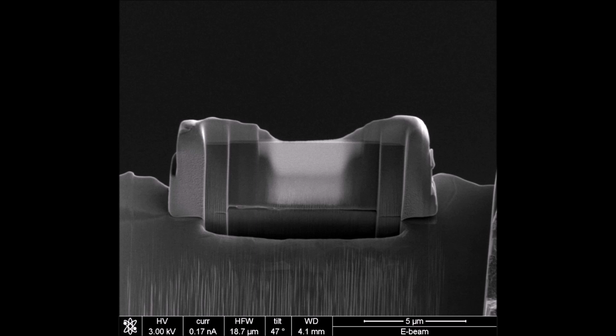So silicon is very nice in the sense that it removes material fairly quickly, and it also mills very cleanly and smoothly. So that's why we're going to use silicon as a demonstrating material, because it really has almost an ideal behavior in terms of its performance when we're talking about using a FIB to prepare a lamella.